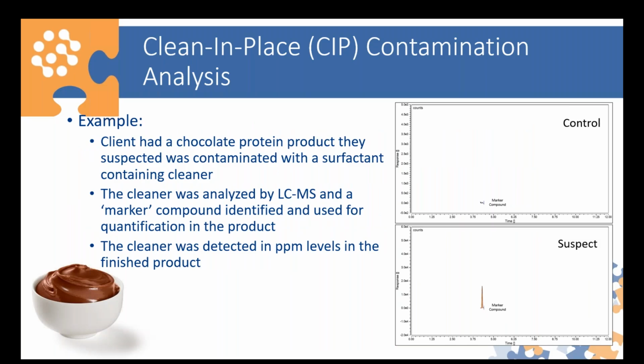For example, we had a client with a chocolate protein product that they suspected might have been contaminated with a surfactant-containing cleaner. What we did here is we obtained a sample of both a control product that they knew was good and a suspect sample that they thought was contaminated, as well as the cleaner itself. Using the cleaner, we were able to analyze it by LC-MS and find what we call a marker compound. This compound we could use as an indicator for the presence or absence of the cleaner.